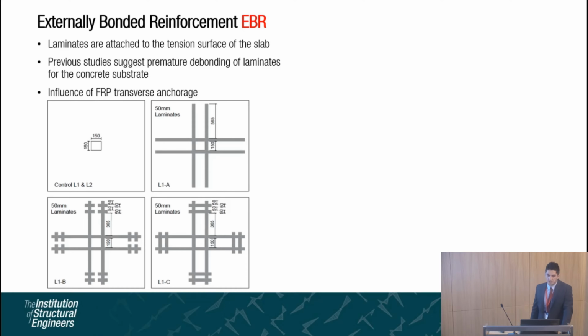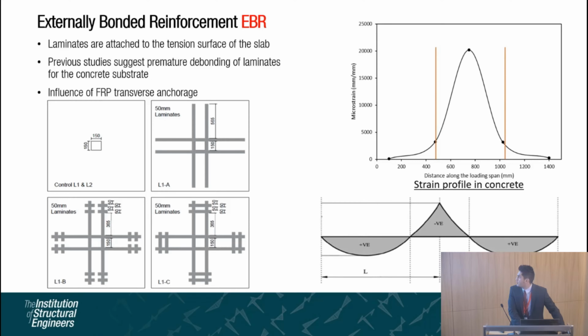So in this first set of experiments, there were 4 slabs. So one was control. The second one was strengthened with FRP, 50 millimeter wide laminates with 1.2 millimeter thickness. At the bottom, in 2 of the samples, the transverse anchorages could be seen. The reason for selection of these anchorages was, initially we tested slabs in order to find the strain profile inside the concrete. And we measured that the strain is very high towards the center of it, and it exponentially decreases as we are going away. So potentially by placing these transverse anchorages, because the strain is very low, the debonding will not occur at those specific regions at lower stages of the loading.